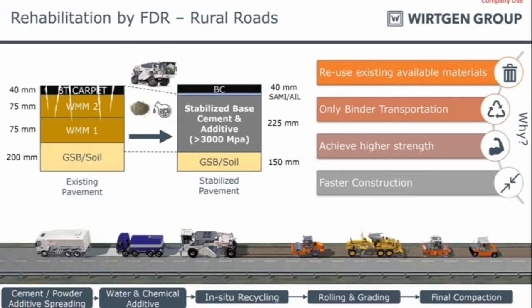This cementitious FDR layer is susceptible to cracking due to drying shrinkage and also due to wheel load induced stresses. To prevent reflection cracking onto the upper part of the pavement from the FDR layer, we need to provide a crack relief layer, either in the form of an aggregate interface layer or a SAMI layer. SAMI stands for stress absorbing membrane interlayer.